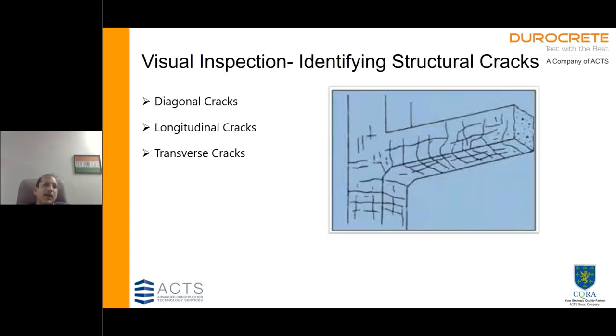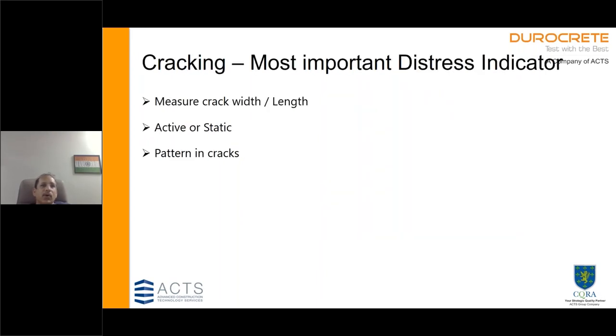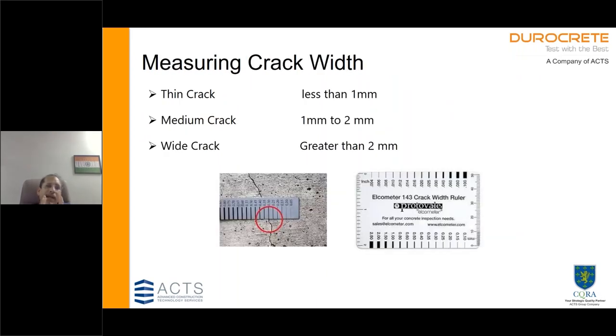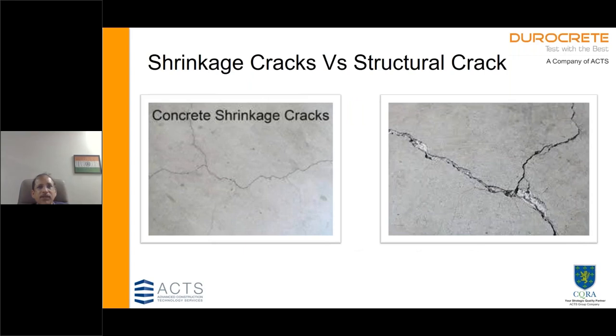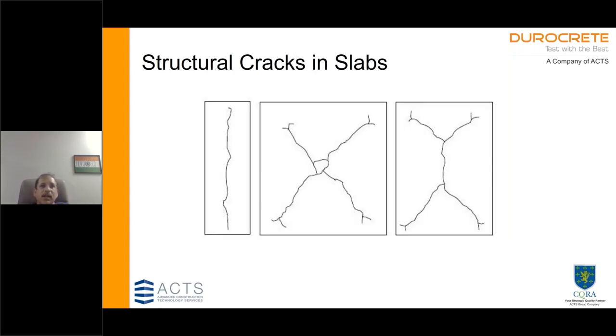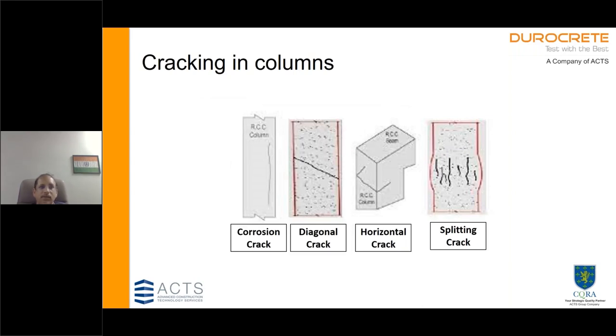When we do a visual inspection, it is very important to identify or differentiate between structural and non-structural cracks. So when we look at cracks, it is important to measure the crack width. These are some of the standard measures of checking the crack width. A scale is available. This is a typical difference between a shrinkage crack and a structural crack; you can see the difference in the crack width. You can see these structural cracks in slabs, and if you are able to identify these cracks early, that proverb of a stitch in time saves nine applies, and many serious problems can be avoided. This is cracking in columns.